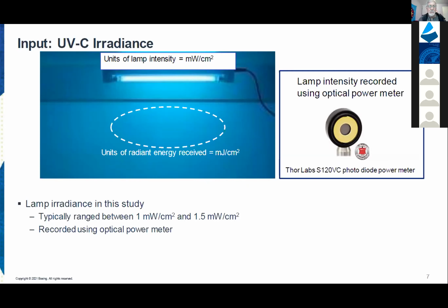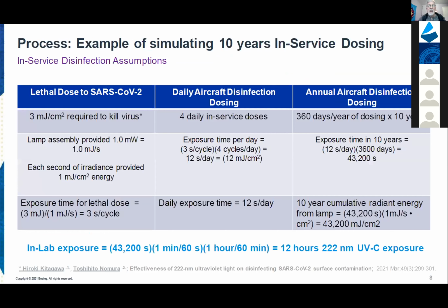And this is something that we routinely recorded and measured using a commercially available power meter from Thor. Now, in our particular study, the lamp irradiance from our lamps did range between 1 milliwatt per square centimeter and 1.5 milliwatts. And again, we typically recorded the irradiance along the long axis of the lamp, and we had samples within roughly about 2 inches from the lamp. So pretty good intensity. Okay, so how do we then go about estimating 10 years of exposure?